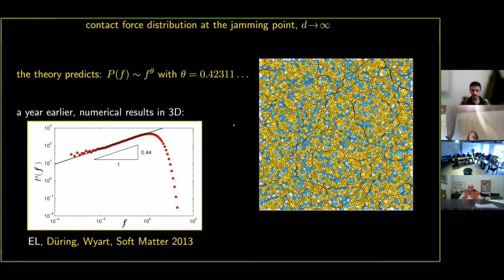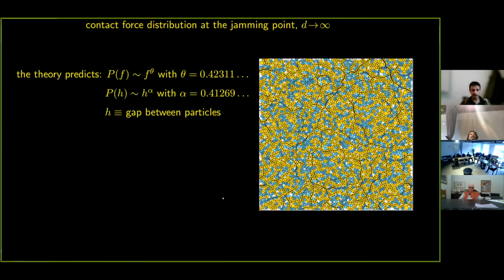I won't go into the details, but there's a reason that it took a long time to be able to measure this in simulations. On top of that, the theory predicts that the distribution of gaps between particles that are not touching, the gap is denoted here by h, grows like h to the alpha with some exponent alpha that's also calculated numerically up to 5th digit by the theory.